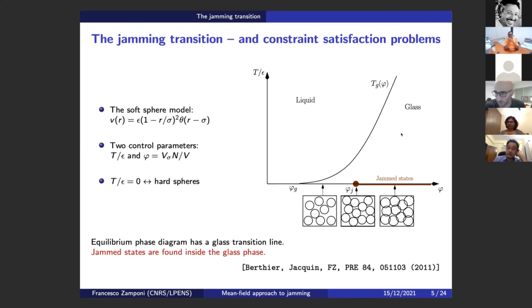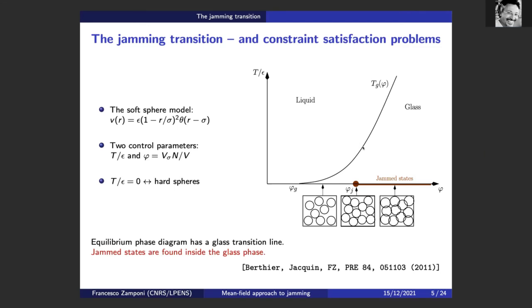No, you're totally right. I'm sorry about that. So in the infinite dimensional limit, in the mean field limit, you have a sharp glass transition that is basically this mode coupling transition where dynamics becomes arrested. In finite dimensions, we have many arguments based on theory, but also direct evidence from numerics and from experiment that this is not a sharp phase transition, it's a crossover. It's a dynamic phenomenon. So the point is that indeed, that's what I was mentioning before.